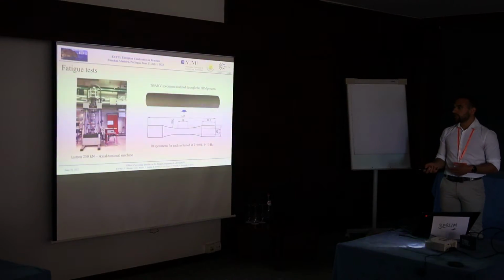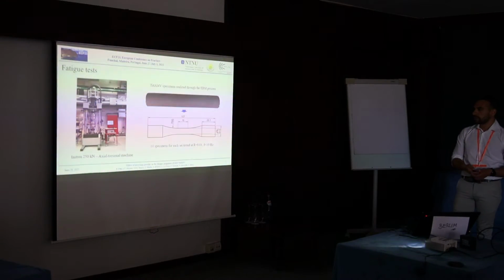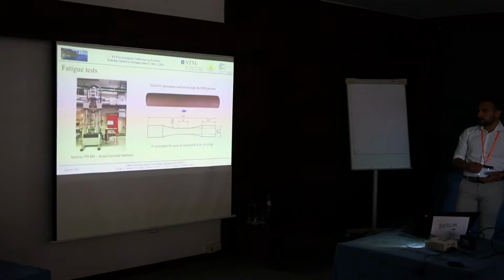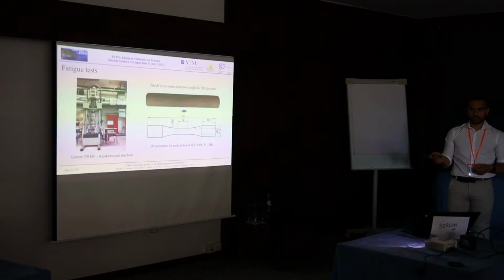About the materials and methods used, we started from some rods built according to the electron beam melting process. We considered these titanium alloys, and for each batch of different powders we considered 10 different specimens that were machined to the final condition, and tested at a load ratio of 0.01 and with a frequency of 10 Hz, using a multi-axial Instron machine of 250 kN. Even if the tests that I'm going to show you now are only carried out in one test condition.